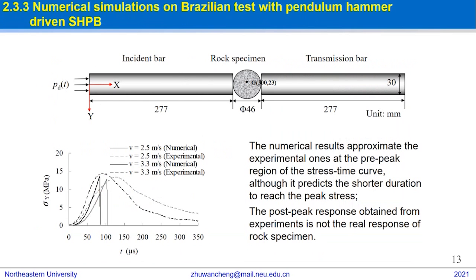This slide shows the numerical simulations on the Brazilian test with pendulum hammer-driven SHPB. The figure above shows the model setup of the numerical simulation of the dynamic Brazilian test. As shown in the figure below, the numerical results approximate the experimental ones at the pre-peak region of the stress-time curve, although it predicts a shorter duration to reach the peak stress. In this regard, the post-peak response obtained from experiments is not the real response of the rock specimen.